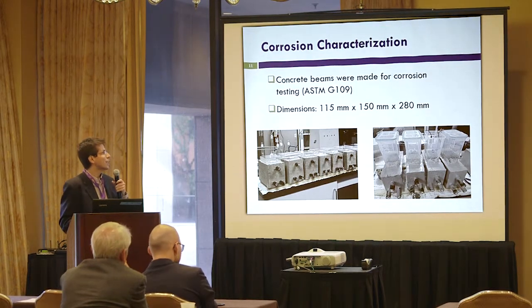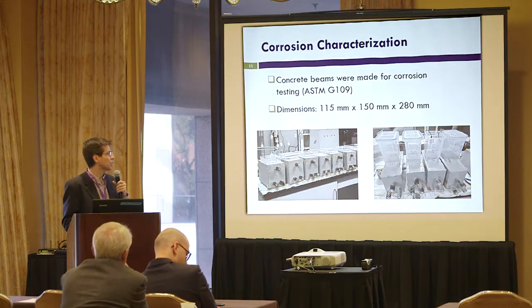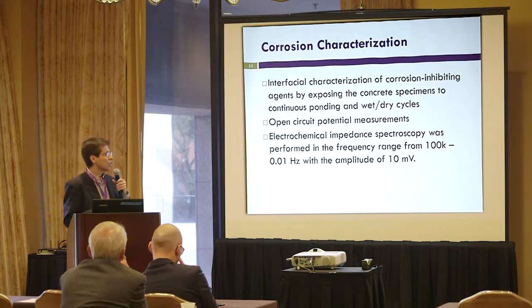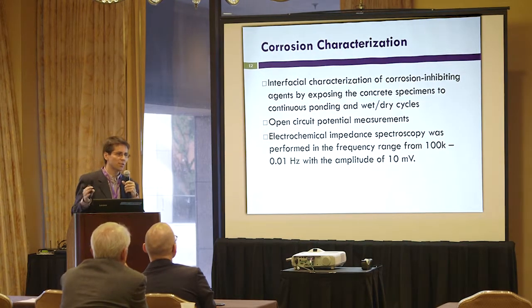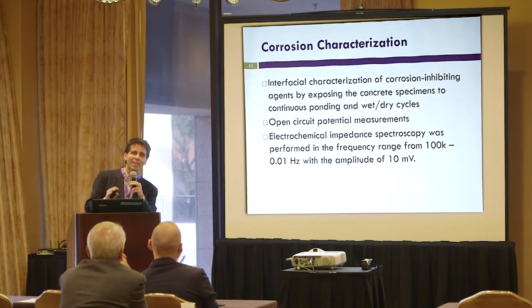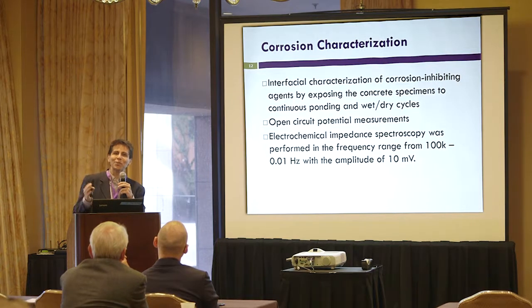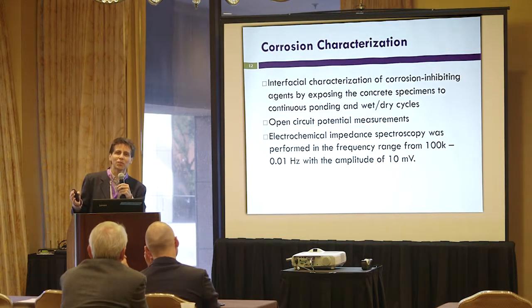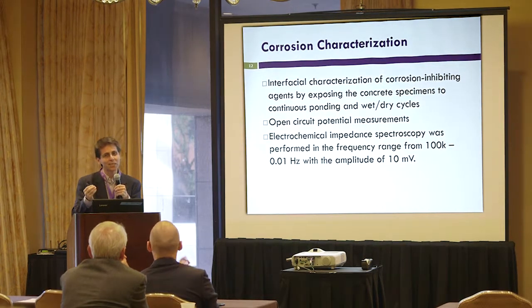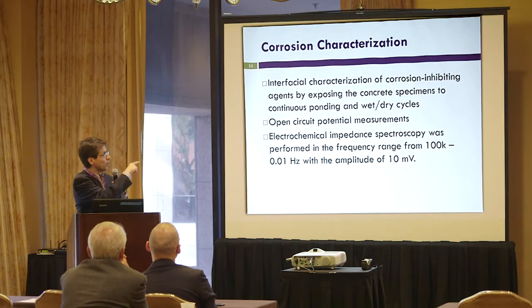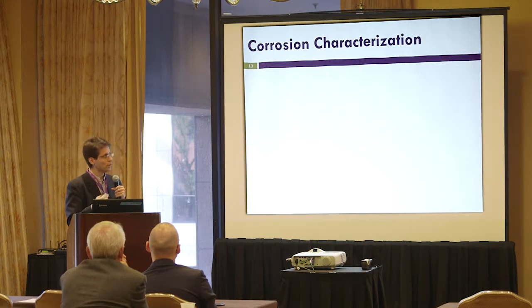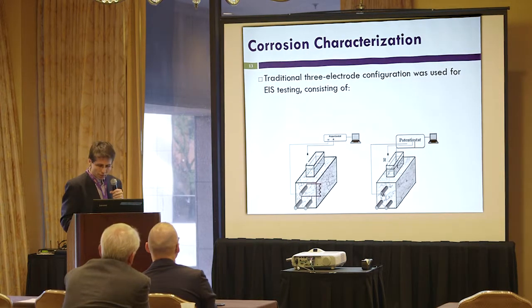We use DC methods and also AC methods, which is new and is a non-destructive evaluation. In terms of corrosion characterization, there is the open circuit potential — in civil engineering everybody just follows the open circuit. But I am starting a campaign to tell civil engineering that potential is a thermodynamic magnitude. Thermodynamics is feasibility; kinetics is what tells you corrosion. We follow the standard, but we also use the corrosion kinetics aspect, which is corrosion rate — not potential versus a reference, which sometimes works and sometimes does not. The DC and AC setup just involves connecting the rebar as the working electrode and using a reference electrode for potential measurements.